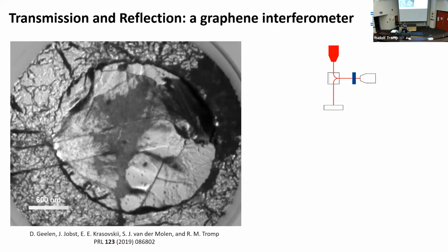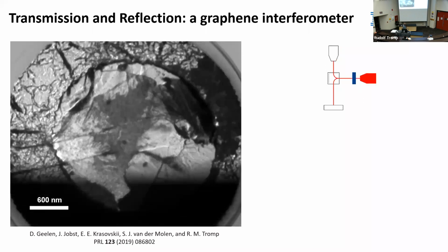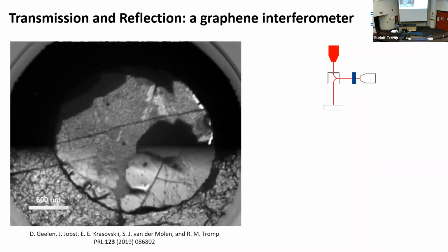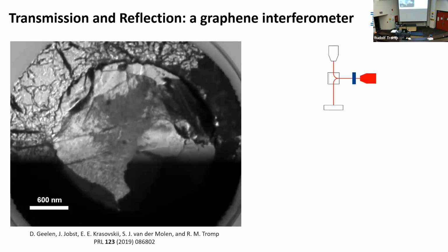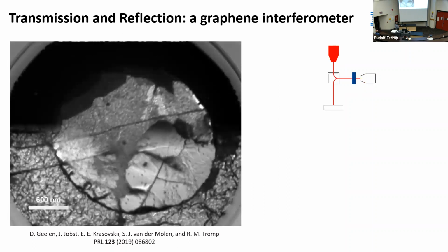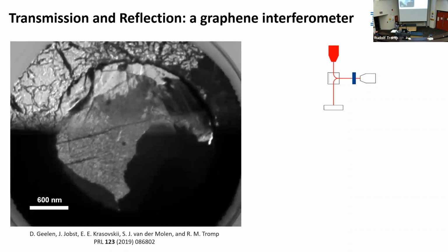Here's an image of a TEM grid. There's a 2 micrometer hole in it. Here we have graphene. This is in reflection. And here we see the same area in transmission, right? So we switch from one electron gun to the other, back and forth, and we get these images.